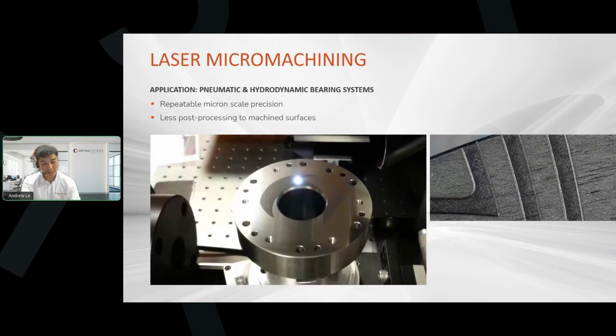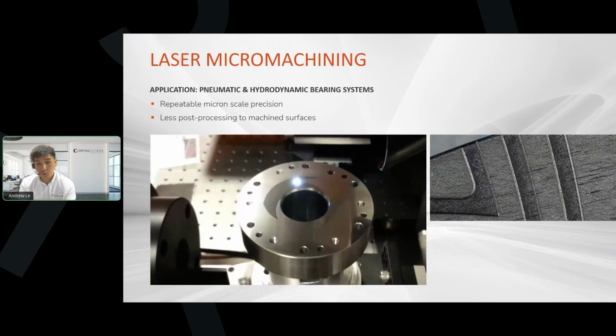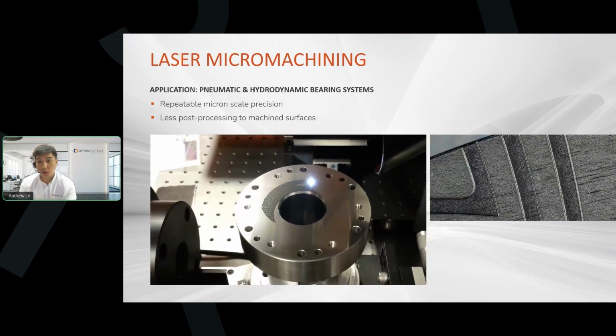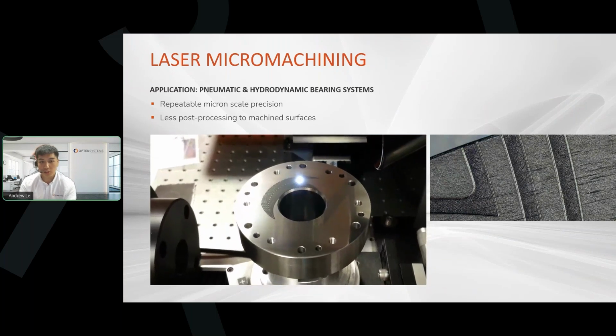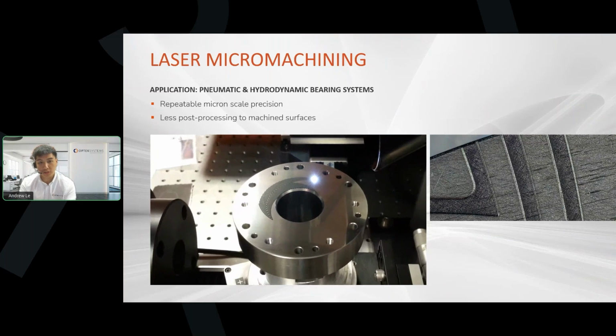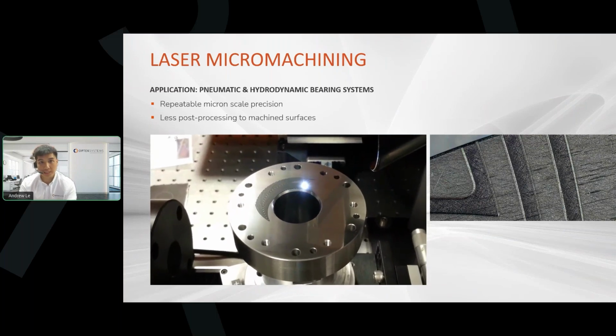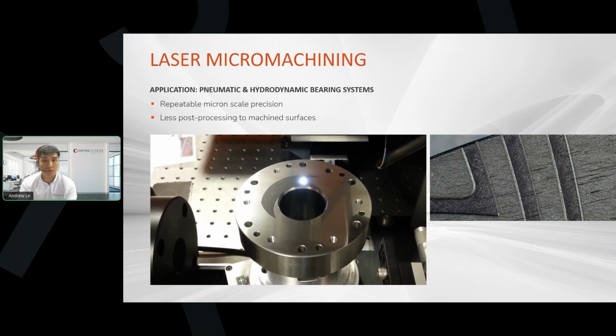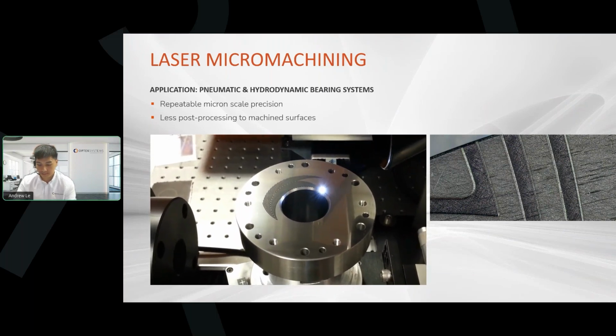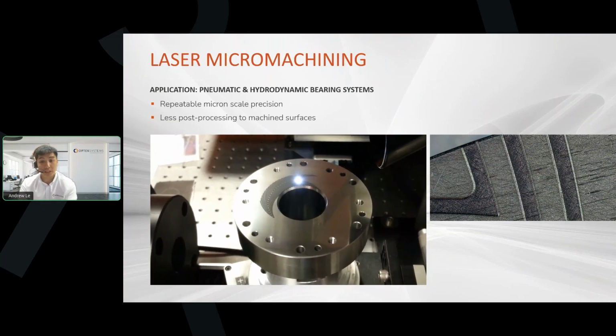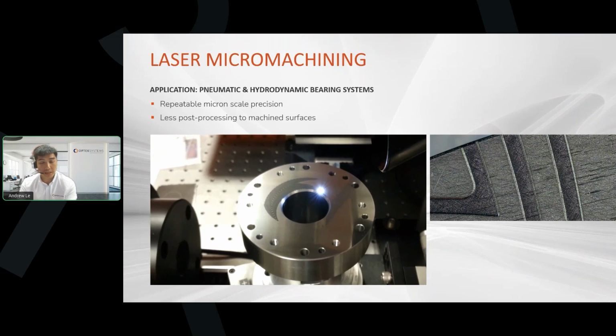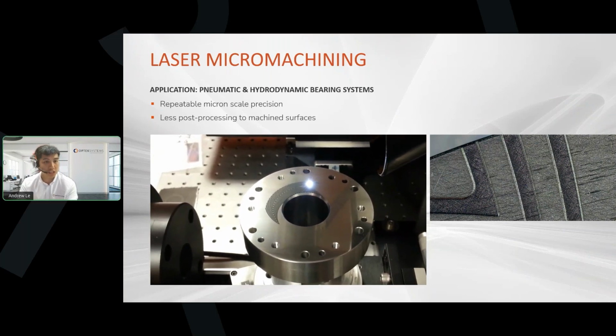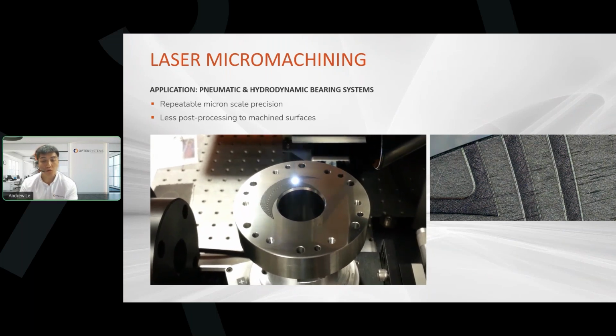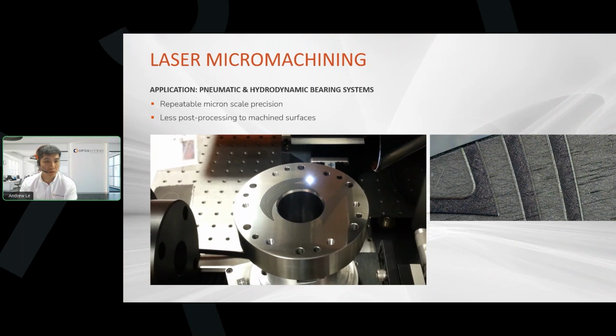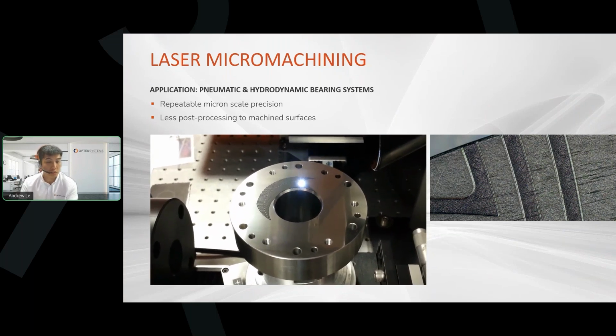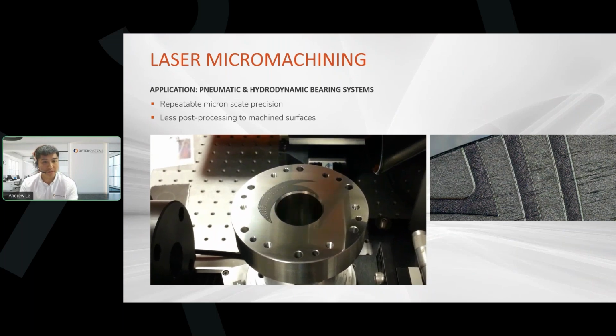Another example of this same topic is that a lot of these pneumatic bearing systems have very specifically treated surfaces with high amounts of polish or with surface treatments. What this means is that we have to minimize the amount of post-processing done in order to preserve those treatments and qualities. OpTek's laser applications labs are able to preserve this by the simple fact that with laser micromachining, we are able to produce features that are nearly ready to go to work right off the laser. This means that there's less post-processing treatment that has to be performed, which could compromise the engraved features on these workpieces.